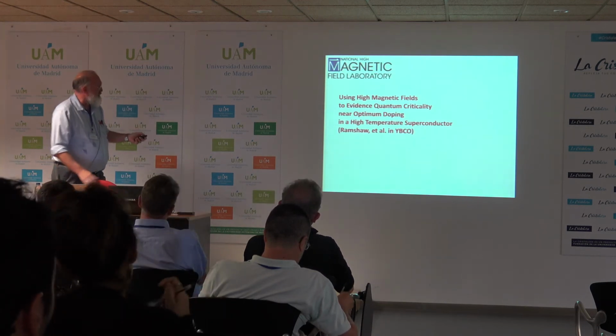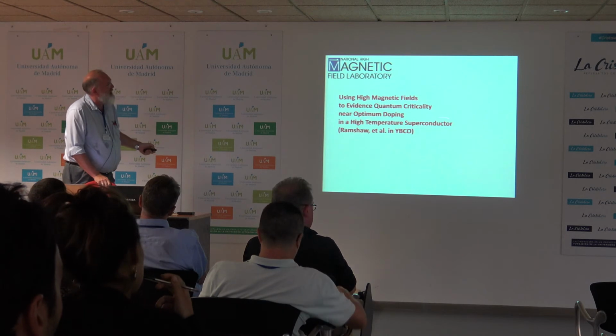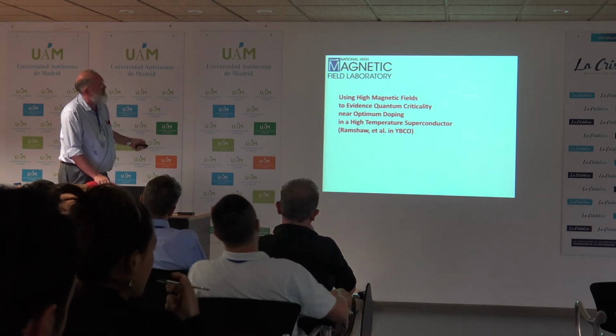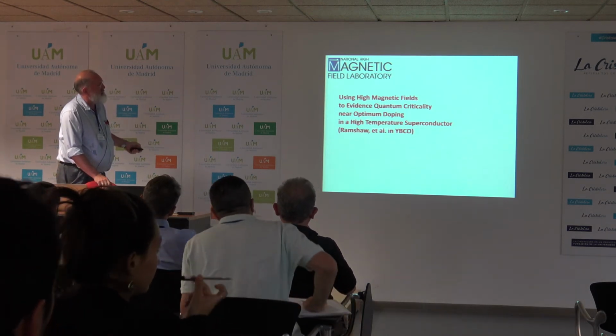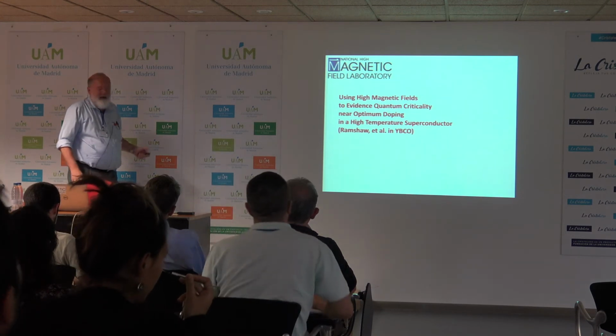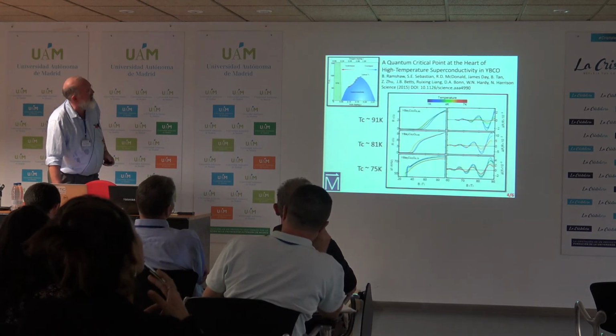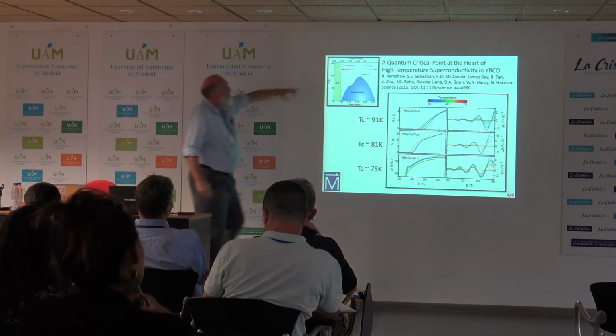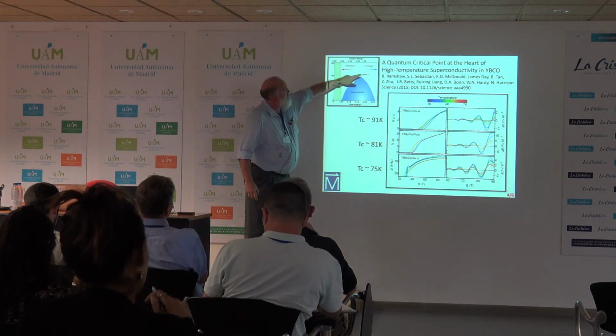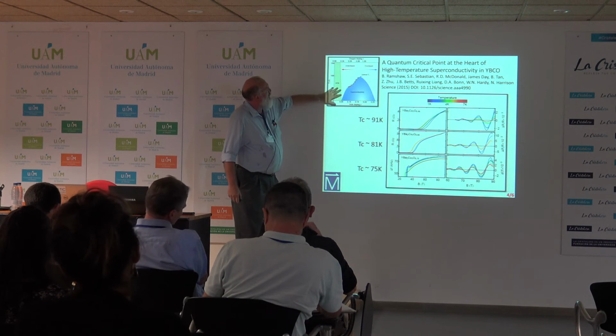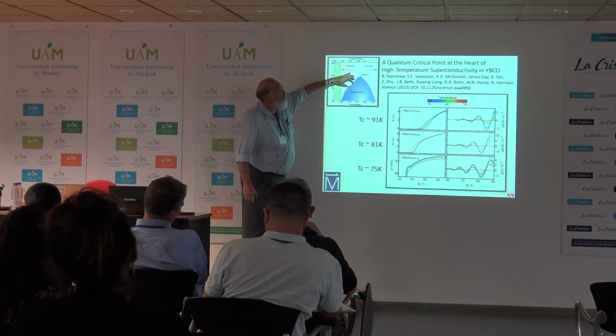So these are data from Brad Ramshaw in YBCO using high magnetic fields to evidence quantum criticality near optimum doping in a high temperature superconductor, and I'll spend some time on quantum oscillations. So this is the regime in the phase diagram. This is the superconducting dome for YBCO, where the quantum oscillations were first observed.